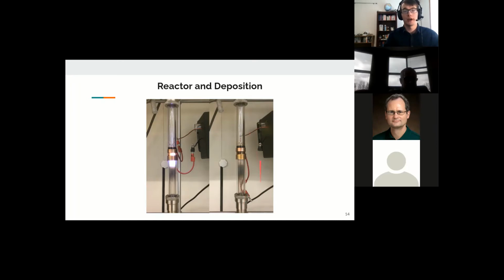The pressure in the reactor was moderated manually using a gate valve and was kept constant for every run, and it was always kept between 5 and 40 torr. During a synthesis reaction, which was typically an hour in length, a considerable amount of deposition forms on the reactor walls. Most of the deposition in the synthesis process happens right around the electrode locations, but some also happens downstream.